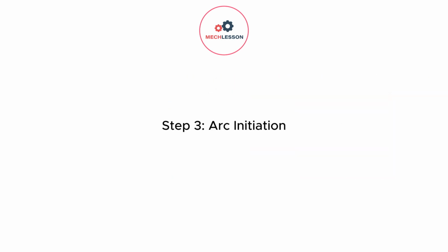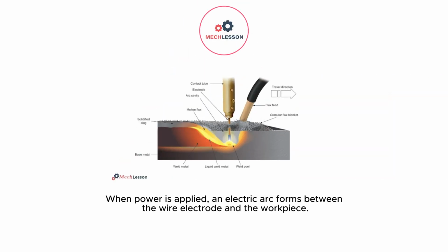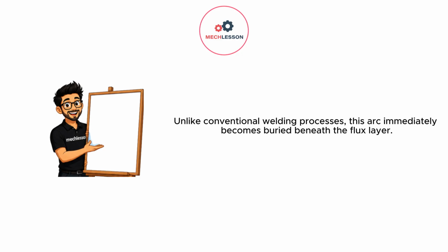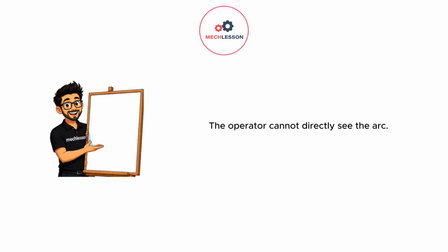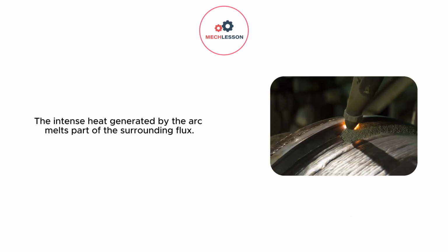Step 3. Arc initiation. When power is applied, an electric arc forms between the wire electrode and the workpiece. Unlike conventional welding processes, this arc immediately becomes buried beneath the flux layer. The operator cannot directly see the arc. Step 4. Flux melting. The intense heat generated by the arc melts part of the surrounding flux. As the flux melts, it forms a layer of molten slag above the weld pool. This molten slag provides additional protection and insulation.